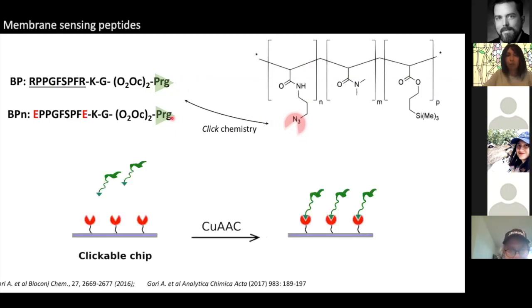So what we do from the practical point of view is to prepare what we call clickable chips, that are silicon slides coated by the functional polymer bearing azido groups that are exposed on the surface in such a way that when we spot the peptides bearing the propargyl glycine, the triple bond, the alkyne group of the glycine is able to react with its orthogonal group on the surface by a well-known click chemistry reaction, which is the copper-catalyzed azide-alkyne cycloaddition. So in this way, we are sure that our peptide is immobilized chemoselectively in an oriented way.